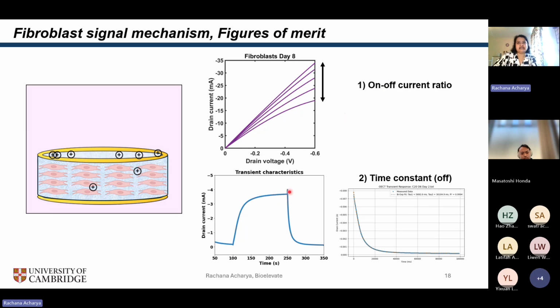The second thing, because we noticed there is a change in the switching off of the transistor, is that I'm going to extract the exponential time constant from my transient measurements and use that as my figure of merit. I want to check how these two metrics change as a function of time as my cells are growing. For that, the way we designed this experiment was to have different rates of cell growth, so that we can check how these metrics change for those different rates.